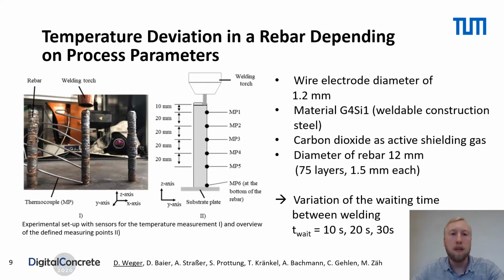Now let's come to the second experiment of this paper, and this experiment was about the temperature deviation in a rebar depending on process parameters. For the test setup, we used a material as welding wire and substrate which was comparable to construction steel. Furthermore, we used carbon dioxide as active shielding gas, and the printed vertical rebars had a diameter of 12 millimeters. For the experiments, we varied the waiting time between the welding with 10 seconds, 20 seconds and 30 seconds, and the temperature was measured at several measuring points on the surface of the rebar.